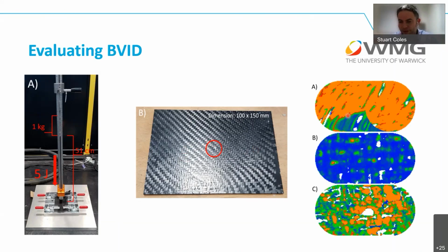We looked at a variety of different imaging techniques, from microscopes and spectroscopic, to try and look at whether we could see different layers and different energy absorptions. We looked at using digital image correlation to look at some of these events, and we couldn't really see anything with those sorts of imagery. These pictures are all largely inconclusive about what was going on in the different layers. That one is an ultrasound, and it doesn't tell us particularly anything. And the ultrasound is what people would traditionally use to diagnose some of these defects and problems. So the ultrasound wouldn't necessarily tell you that there was an issue here.